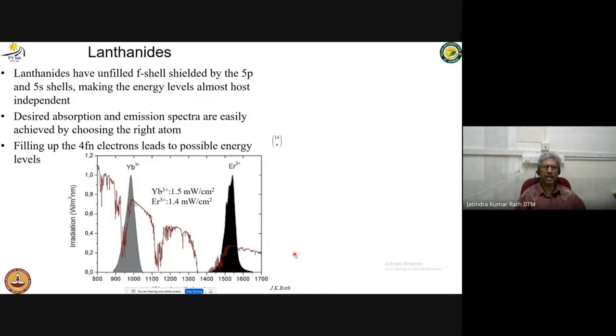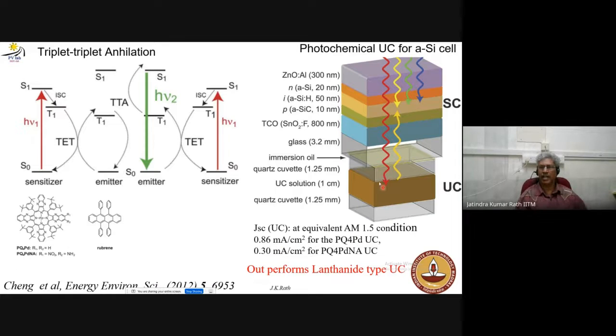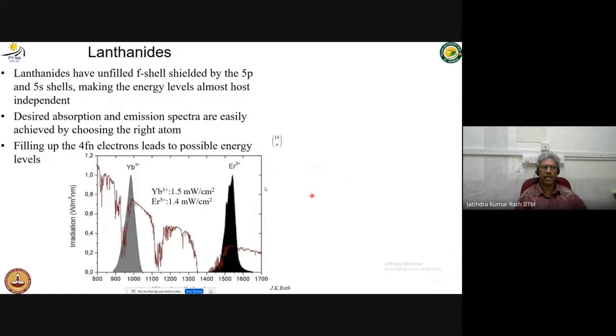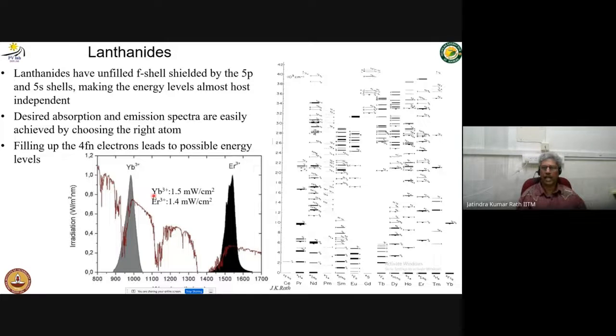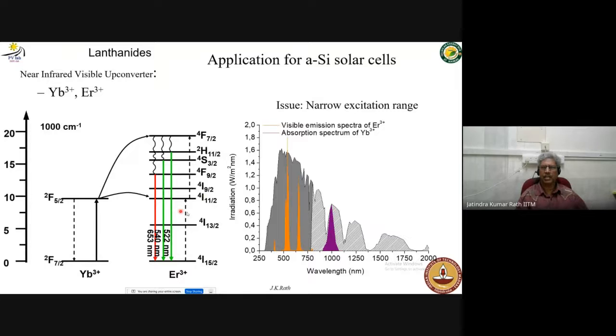But in reality, you cannot have a cell like this hanging somewhere here, so you have to embed it in the system. Lanthanide types of materials can be good host materials in which you can put ytterbium and erbium together, and you can have up conversion. Ytterbium absorbs light and can excite the erbium, so it can go to a higher level, and then from there you can have an emission. This is how the up conversion takes place.